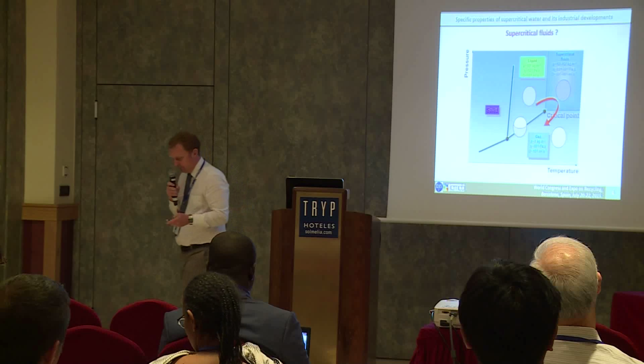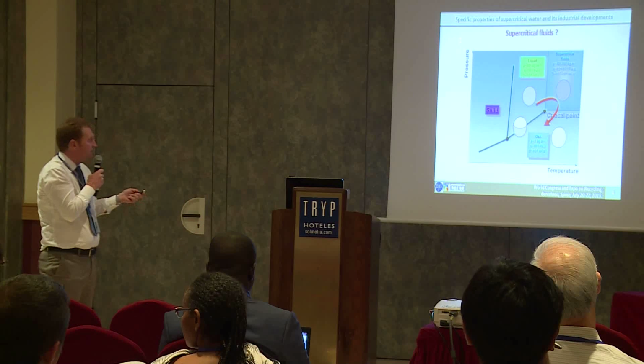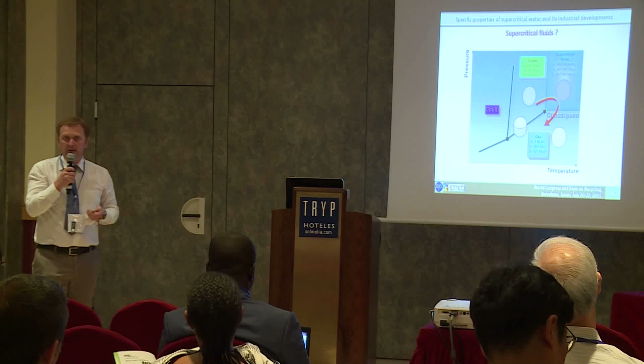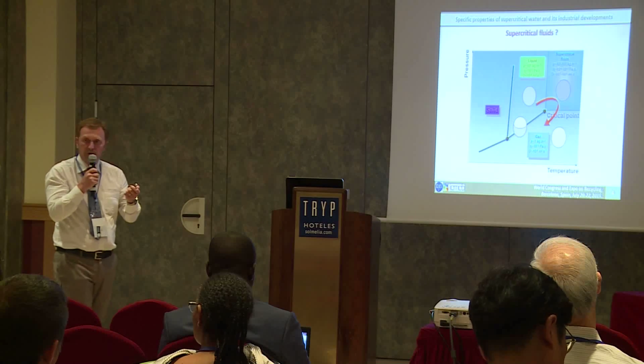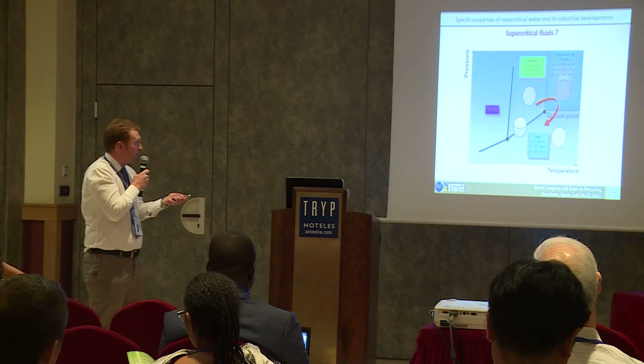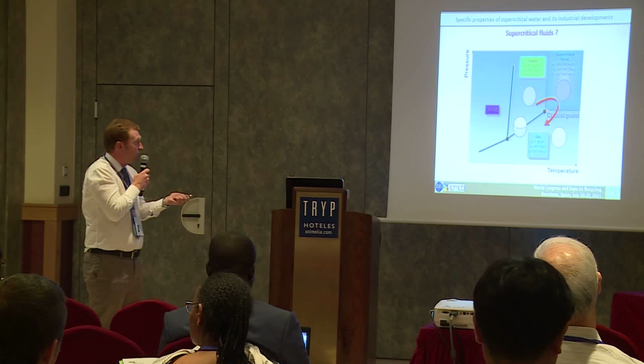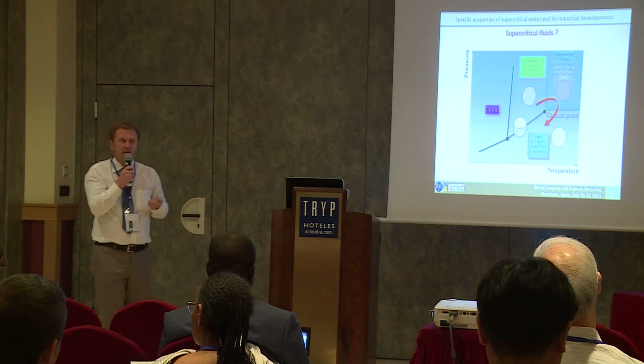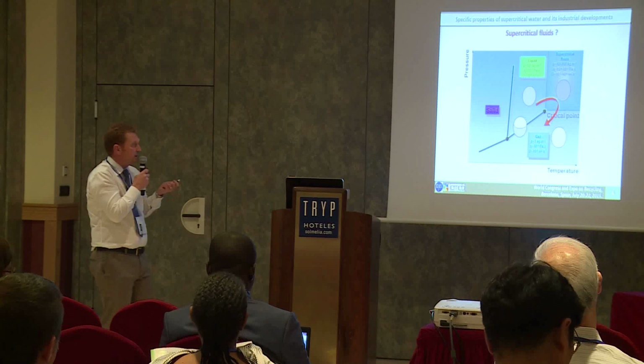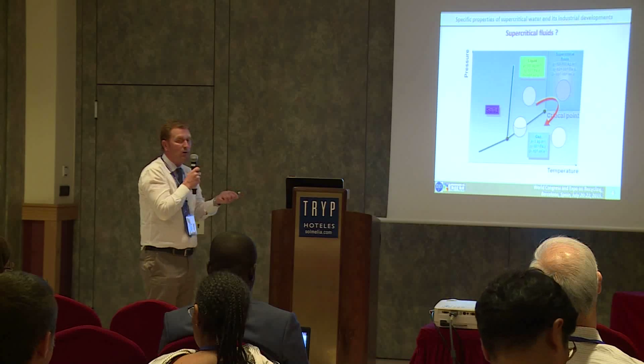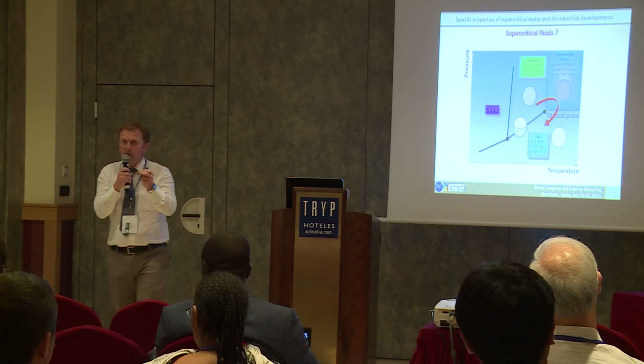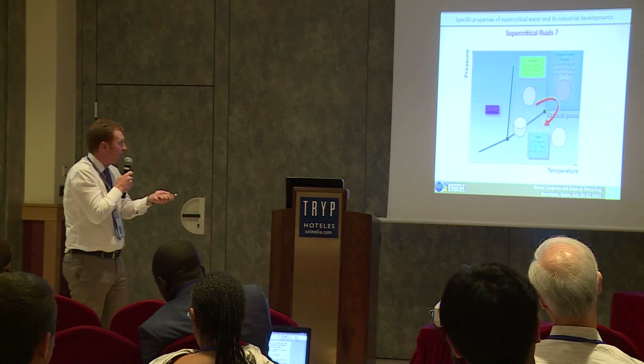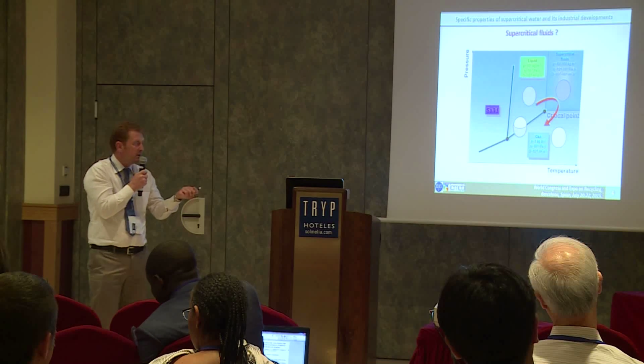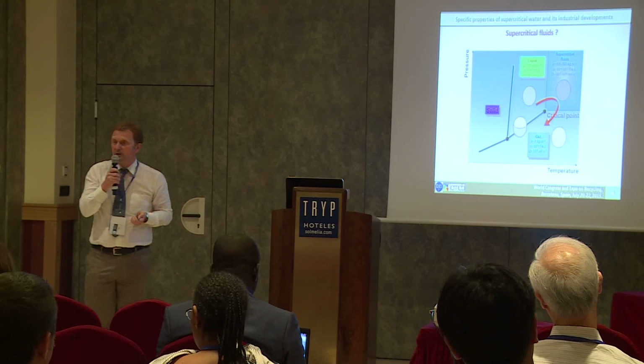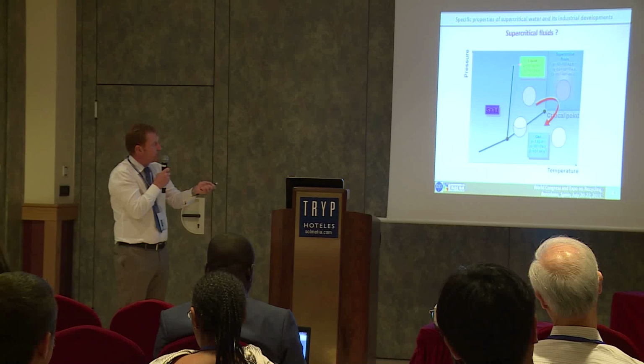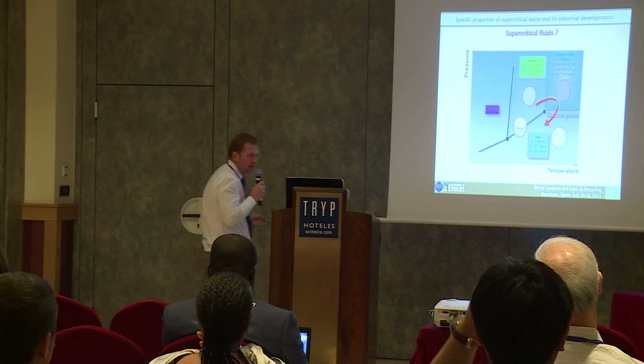So, a supercritical fluid, for the chemist, as you can see on this diagram of pressure as a function of temperature, is just a solvent you are using in specific conditions of pressure and temperature: at a pressure above the critical pressure of the fluid, and at a temperature above the critical temperature of the concerned fluid. What is very interesting with this kind of fluids, as you can see with the red arrow, is that you can precisely tune the properties of your fluid just by changing pressure and temperature. You can tune these properties from the properties of a liquid to the properties of a gas, as you can see here, as an example, with the density, viscosity, and diffusivity.